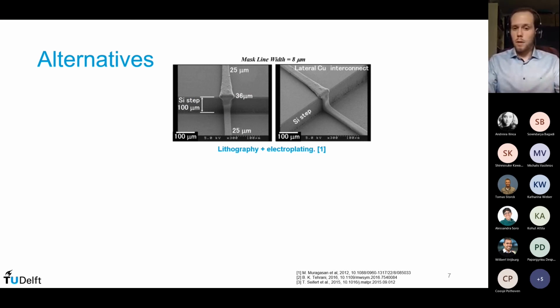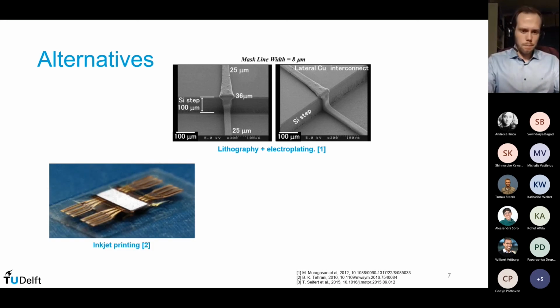Here are a few examples. So people have been trying to do lithography with electroplating to create well-defined lines over this step. So basically, you go on the side of the chip to create this connection. This works, but requires several processing steps and a lot of chemistry to get this right. So it's not as easy or elegant as wire bonding. So people looked into inkjet printing, which is quite fast and can create the type of connection that people need, but is limited to primarily flat substrates because you are basically working as a regular inkjet printing.